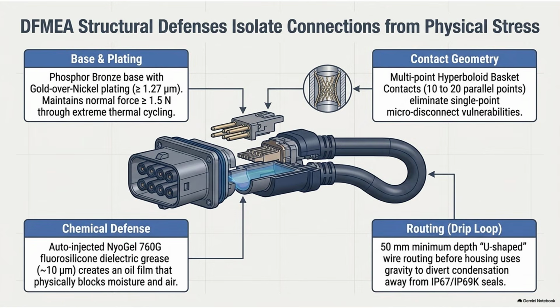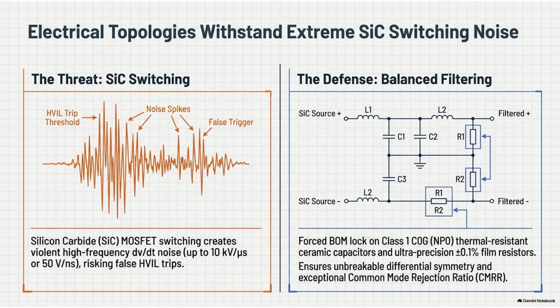But why mandate a layer of nickel underneath the gold? Why not just plate the gold directly onto the phosphor bronze base? That requirement solves a fascinating, almost invisible problem in material science. If you plate pure gold directly onto a copper-based alloy like phosphor bronze, over time, and especially when exposed to the 150 degrees Celsius operating temperatures, the copper atoms possess enough thermal energy to literally migrate up right through the crystalline lattice structure of the gold layer.